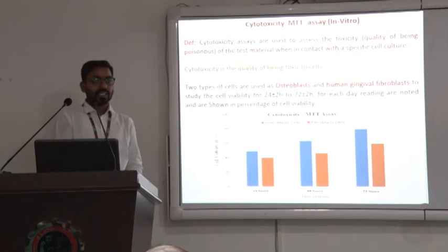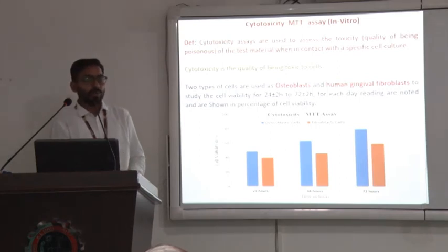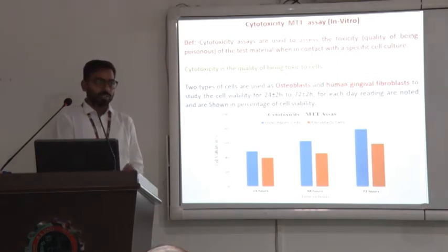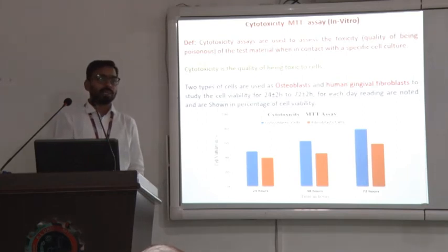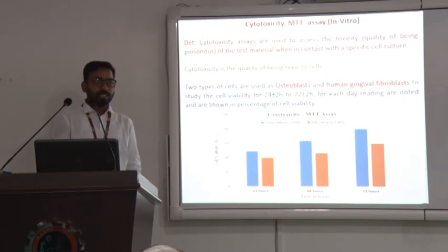These tests are conducted in a CO2 incubator for a period of 72 hours, where we apply the cell line on these samples, supply continuous oxygen and maintain body temperature at 37 degrees Celsius, and observe how the cells react with the laser deposited sample.